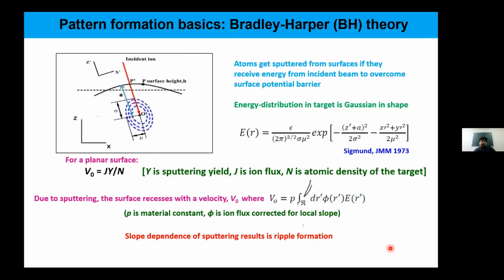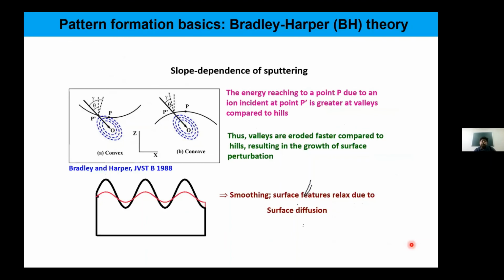So slope dependence of sputtering results in the ripple formation. Why? Because as the energy reaches a point P, look here, due to an ion incident at point P prime, then basically the energy reaching at the point P will be greater at the valleys compared to the hills. So valleys will be eroded faster compared to the hills, which will result in the growth of surface perturbation, surface instability.